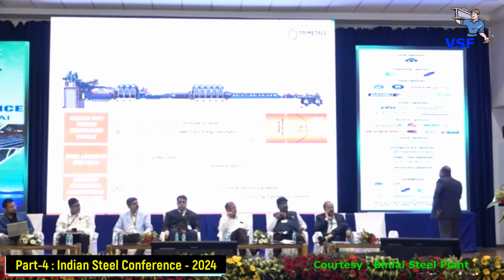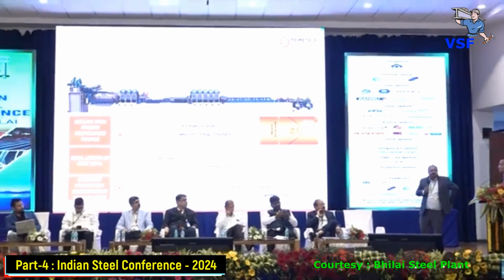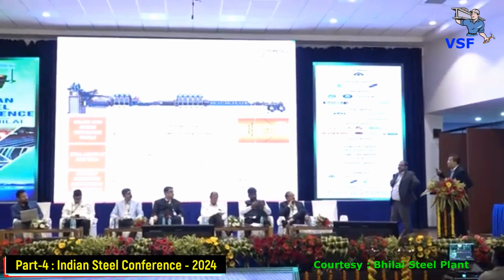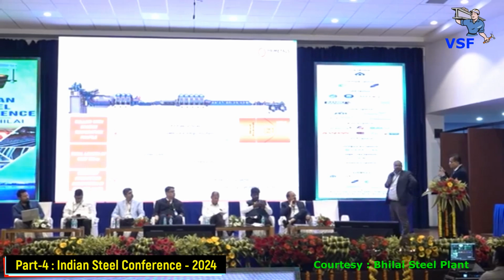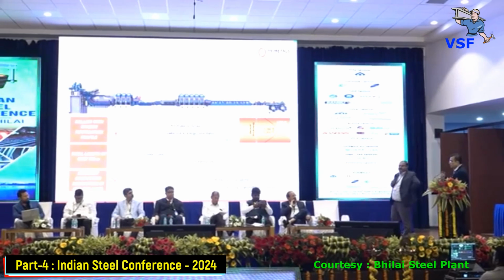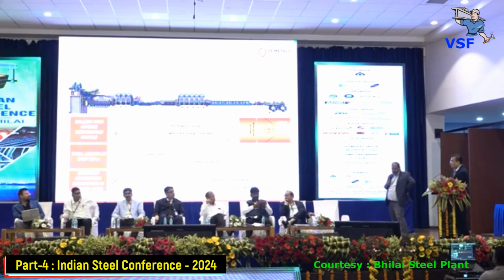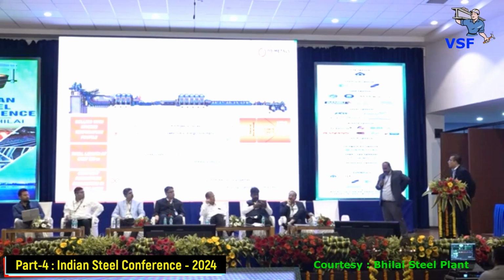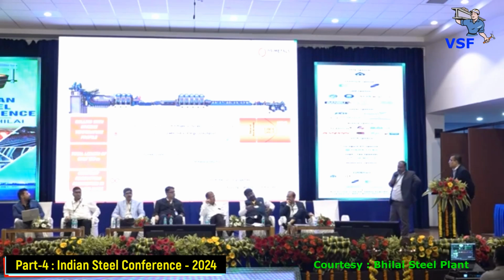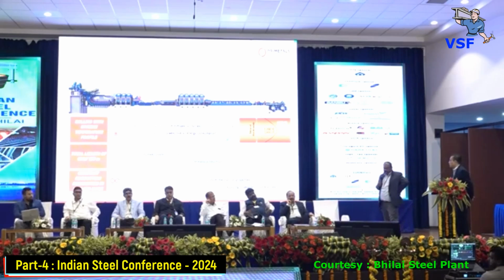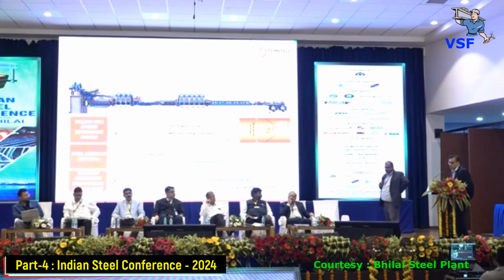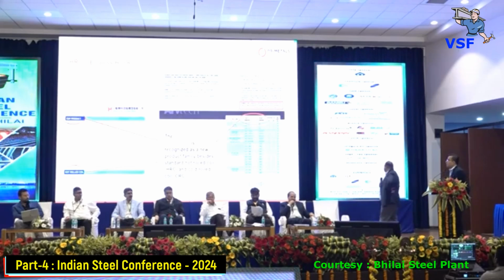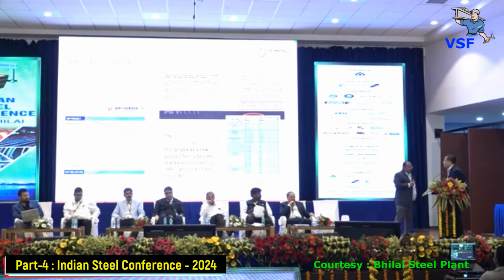Yeah, another point which I want to add with Costa, which is a very nice one. Since we have this transversal heating system, it just moves when the strip comes, because the homogeneity has to be maintained. So it automatically moves. So it's a very stable process we have. And you can see the length of the line is about 180. And since it is a stable process, we can guarantee uniform mechanical properties, and you can tune into the proper geometrical tolerances.